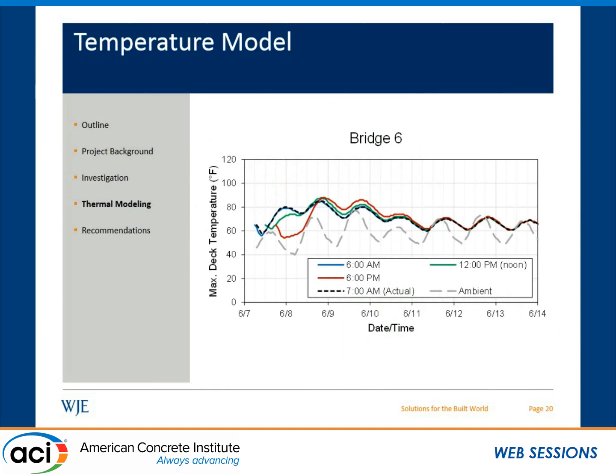Now the other curves I want to point out are these colored ones. We also decided to simulate other placement times. So in blue, we have a 6 a.m. placement time, which naturally would look very similar to the 7 a.m. placement time that we have in black. In green, we have a noon placement time, and you see that the peak is starting to shift. And when we start placing in the late evening with this red curve here, which is a 6 p.m. placement time, what you see is that the peak temperature occurs a full day into the hydration cycle, and it occurs at a later time, which means that the concrete has had greater time to develop tensile capacity. So it can actually handle these differences much better.